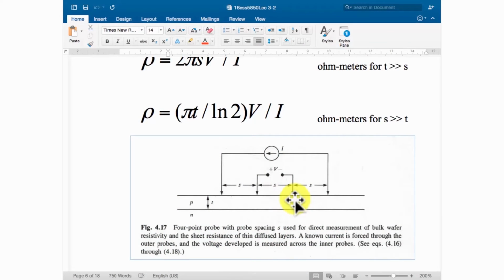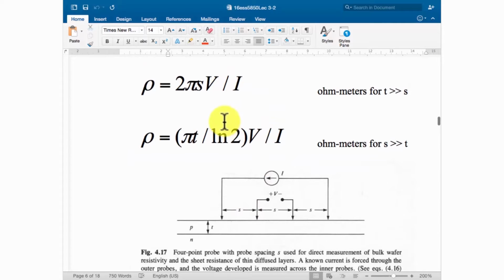So to prevent this kind of situation, to take out the interference of the contact resistance, now we have 4 probes in contact with the surface. All the probes have contact resistance, but we give it a real current. So we know the current, and we measure the voltage. So the current and the voltage are the real measurements, and we plug them into the equation. The equation is found by integrating the current and those kinds of things to become potential. And finally, we got these 2 equations.